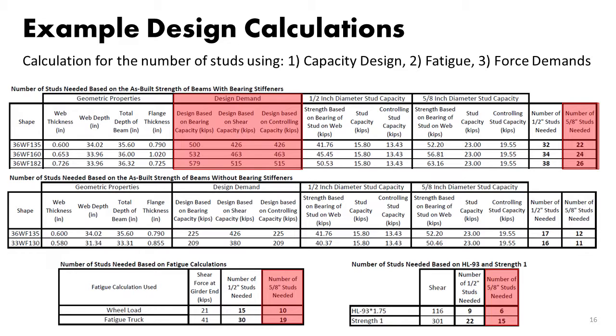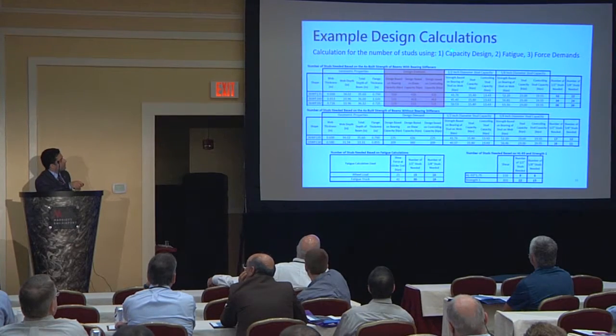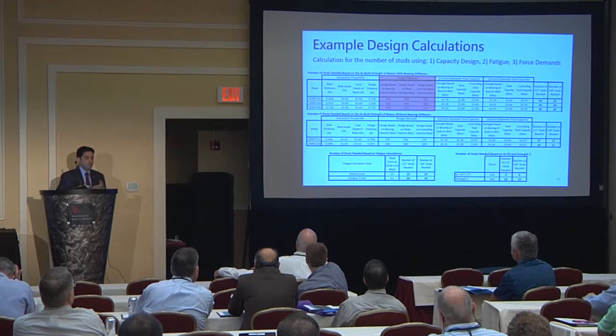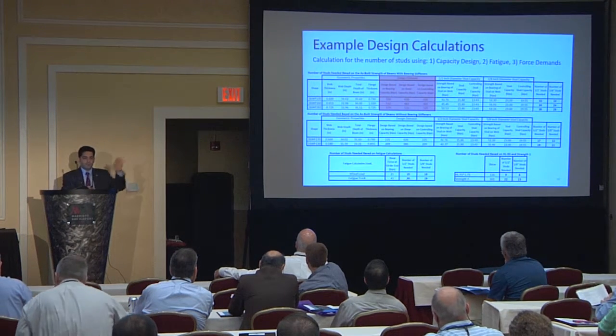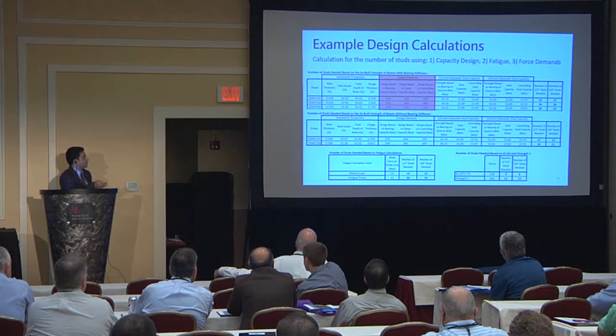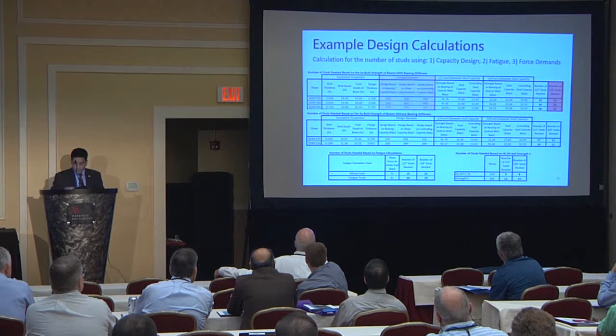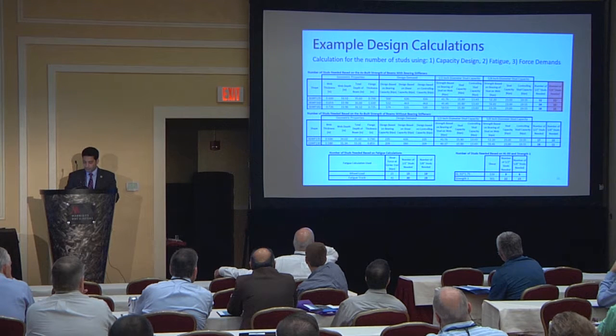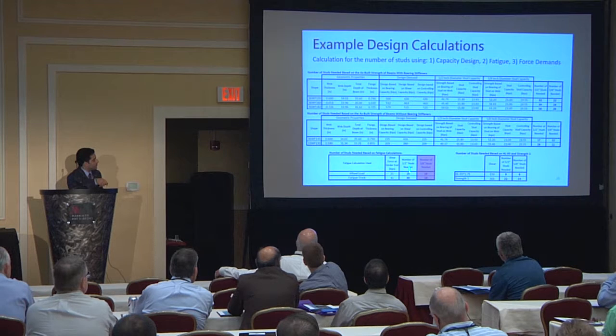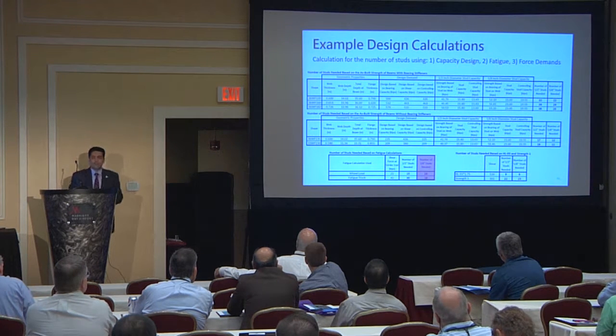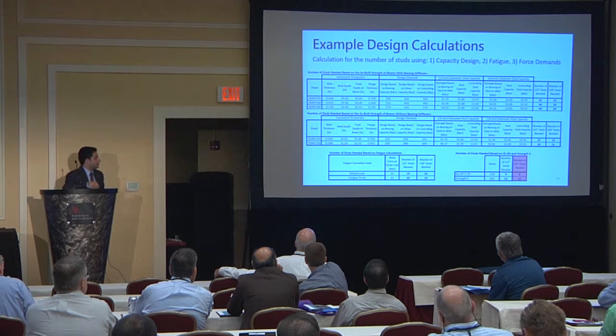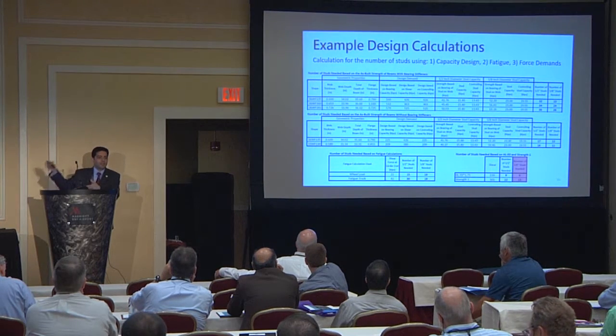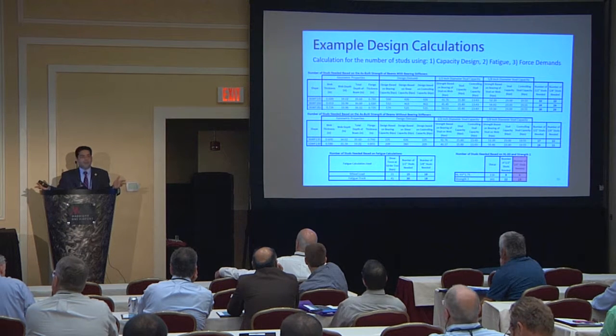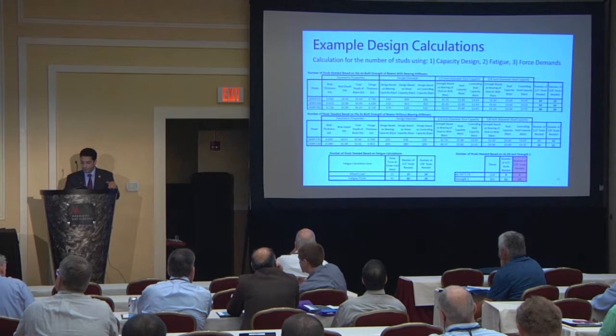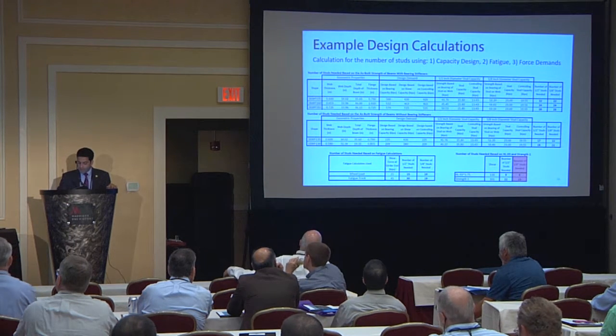And that shows the philosophy that we followed. Here, we explored three different design forces. One is based on the existing shear capacity or bearing capacity from AASHTO's equations. We try to provide enough studs to provide that capacity, which is very conservative. And with that, we can get the number of studs that we need for the beam. Also, we see how many studs we need based on AASHTO's fatigue calculation, and what if you want to use the Strength I load combination. You can see capacity design gives the highest number of studs, but you don't need that. That's essentially the full capacity of a beam, and even in the original design, we don't design for that force.